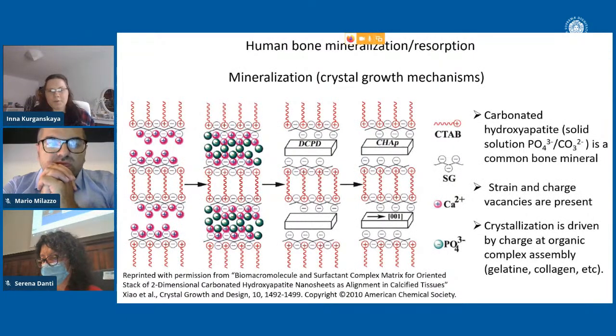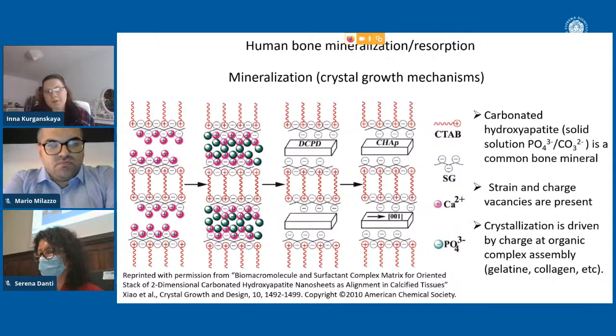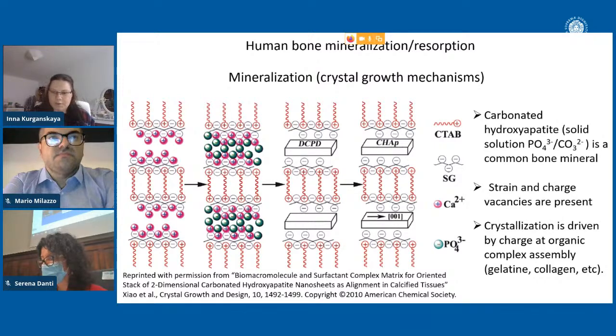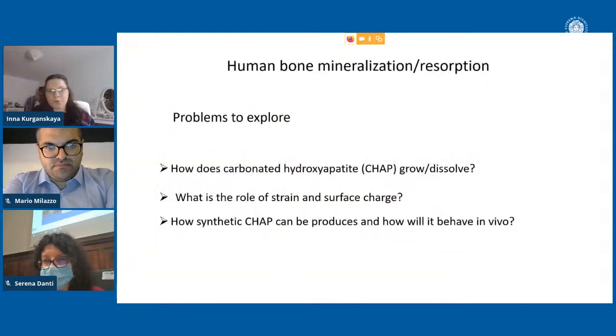Another interesting problem, which is closely related to the problem of solid solution behavior, is human bone mineralization or resorption. The major mineral in human bones is hydroxyapatite, in particular carbonated hydroxyapatite. It means it's a solid solution again, but here the orthophosphate ion is substituted by the carbonate ion, and this change introduces some strain and definitely charge vacancies. Many experiments show that crystallization is driven by the surface charge. It's the organic complex assembly, whether it is gelatin, collagen, whatever, which generates some kind of surface charge, and the surface charge electrostatically attracts the material, pretty much calcium and phosphate, and the material starts to grow. So these are interesting problems to explore in my case.